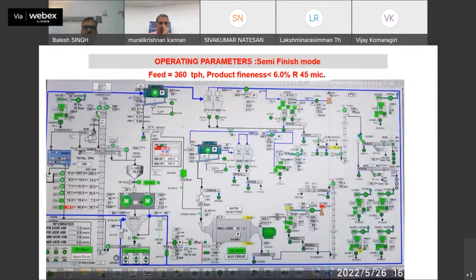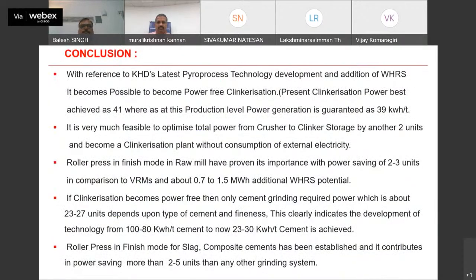Here I would like to inform that it is only possible because in that ball mill the grinding media utilized is less than 70 mm, and that happens because of the softer clinker grindability and smaller size clinker. Otherwise, if the clinker size is bigger and the clinker is harder, then we have to utilize 90 mm balls. That will definitely increase the power consumption for this system. So this is what I have shared, with reference to the latest pyroprocess technology development, and in addition to WHR, it becomes possible to achieve power free clinkerization.